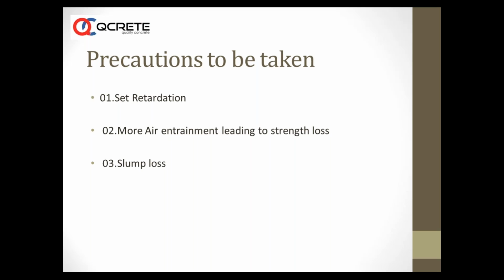Next one is, you have some manufacturers who use air entrainment admixture, who blend it with maybe PCs, maybe with SNF admixtures for various reasons to make the concrete viscous or cohesive. In such cases, we need to remember that higher the dosage that we use, lesser the strength it will become, because more amount of air will be entrained. So we need to be aware that we need to take care of the density. We need to check the density of concrete continuously to monitor the performance of concrete.